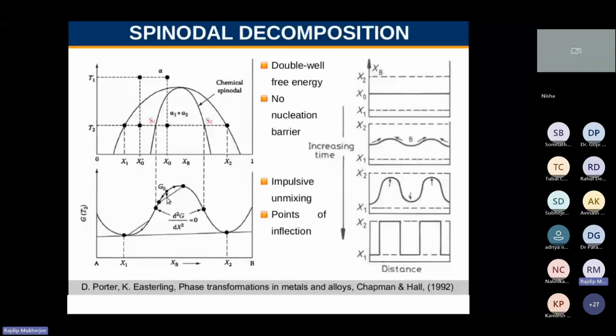Whereas if you are outside this spinodal region, you can still get alpha 1 plus alpha 2, and this can happen through nucleation and growth. So both of these are incorporated in our model. So you can either see spinodal decomposition or a precipitation, right?